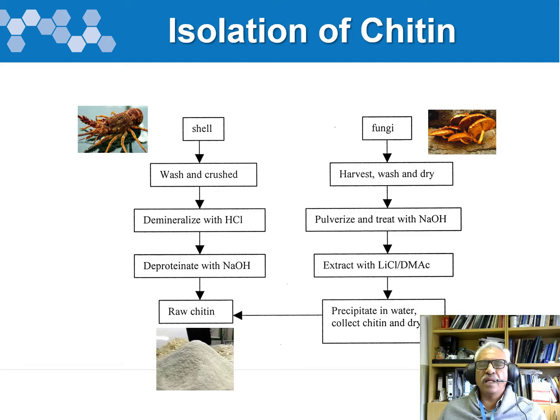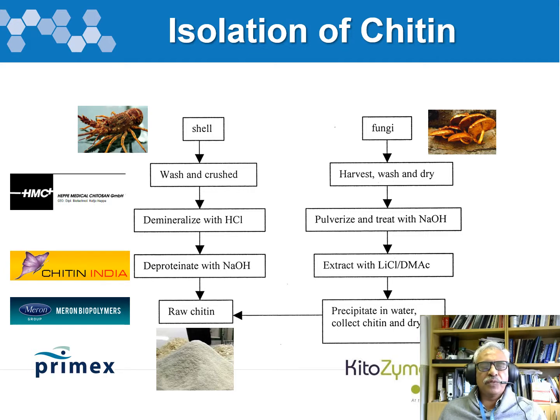Chitin itself is very easy to isolate from fungi. It doesn't require very aggressive chemicals. It's basically treated with sodium hydroxide, and you extract that into dimethylacetamide as a solvent in conjunction with lithium chloride, and it's very insoluble in water, so it will precipitate, and then you can isolate and dry it. Whereas with the shell, you need to wash, crush, and then demineralize it, because unlike the fungi it's got a lot of calcium biomineralized with the chitin. Then you have to remove the protein with sodium hydroxide, and then you get your raw chitin. These are just companies that are producing chitin, and some that go a bit further by making a high quality, high purity medical application chitin and chitosan as well.